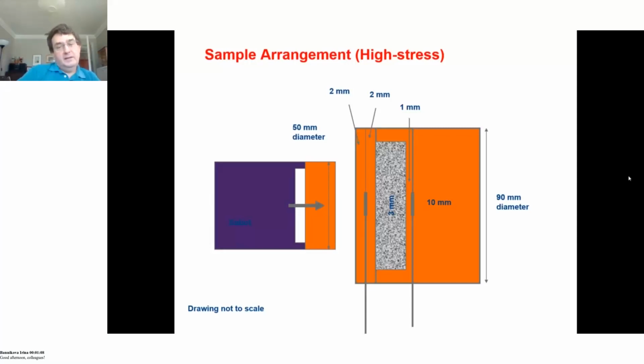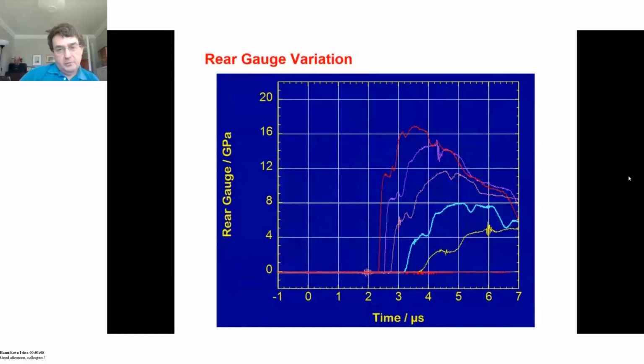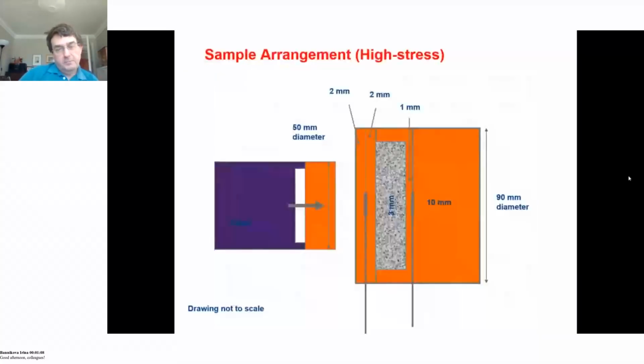And this is the output we got from the rear gauge. So on the front gauge, you measure the input pulse from the copper on copper impact. That's a very generally square kind of pulse. You then have a reflection from the sand layer, coming back to that gauge, and then you measure what goes through the system. Now, because we know the dimensions here and they are consistent from experiment to experiment, we can do a calculation based on time of impact. Sorry, time of stress arriving at the front gauge, time of stress arriving at the rear gauge.